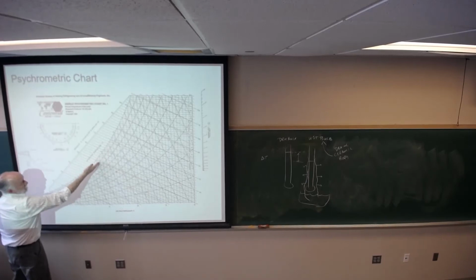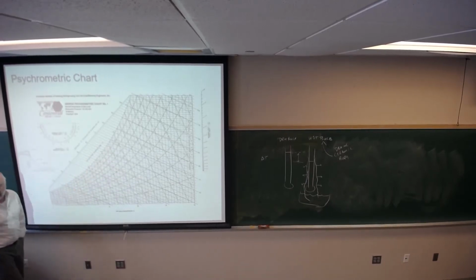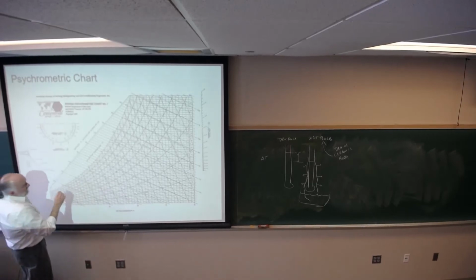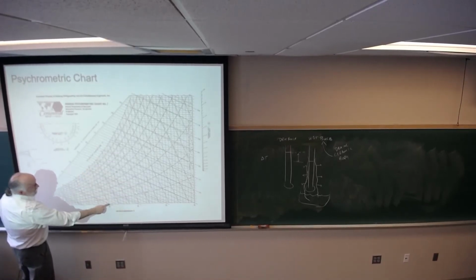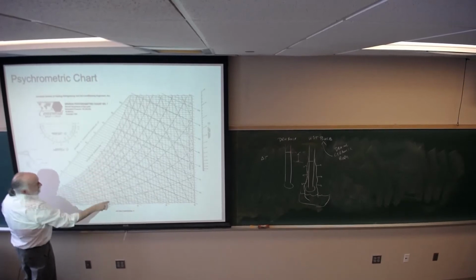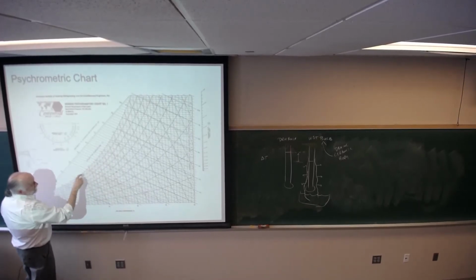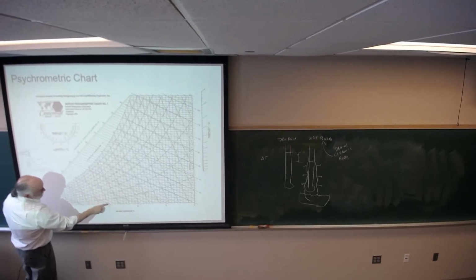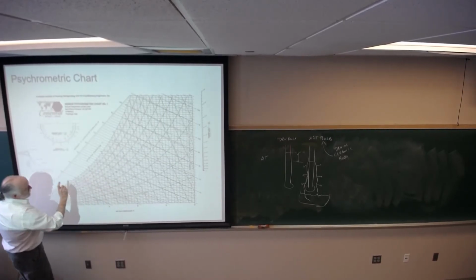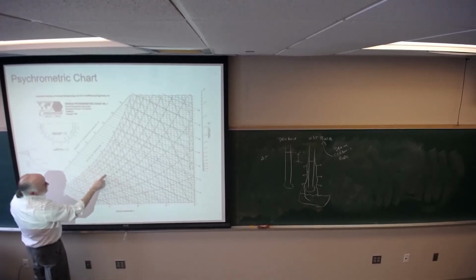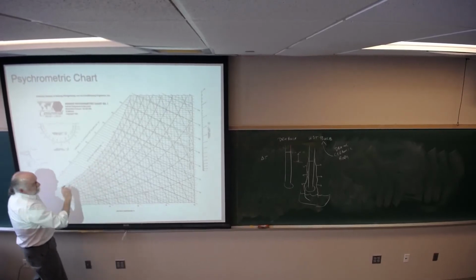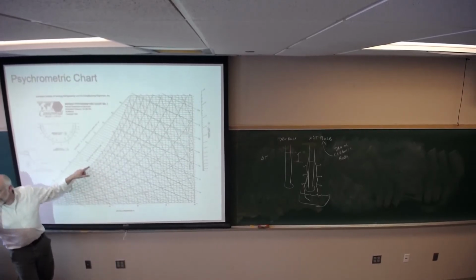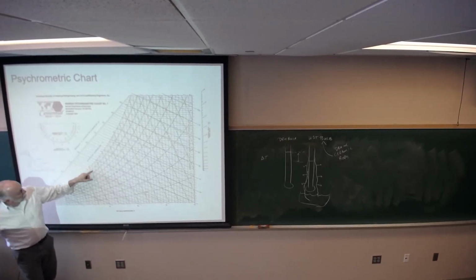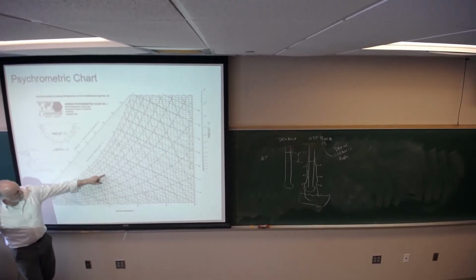This is 100%. Here's 90, 80, 70, 60, 50, and you can't really see that. And then you have lines here like this. So if you were at, say, 20 degrees C, and your wet bulb is 15, you come across to where it hits 20. Wrong line. The right line here, the dash lines. You come across to here where you hit 20. If your wet bulb temperature is 15 and your dry bulb temperature is 20, where they intersect tells you your relative humidity, which is 60%.